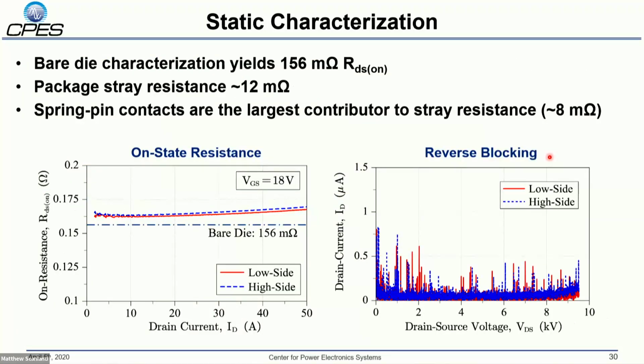This is a look at some of the static characterization results. The only thing I really want to point out here is the discrepancy from what we expect the module to be, the 156 milliohm RDS(on), compared to what it actually is, which is about 168 milliohm RDS(on). So I did some work trying to track down where exactly we were picking up that stray resistance, because it's a little bit higher than what I predicted in the simulation.